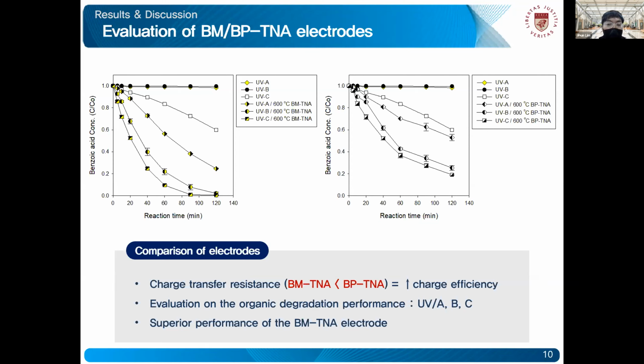Taking a look at the figure on the left, we can see that using the BMTNA electrode, benzoic acid was nearly completely decomposed, with even the minimum decomposition rate being 80%. But on the right side, using the BPTNA electrode, the degradation performance was quite low, and even the highest was only up to 80%, with the lowest being around 40%. So we confirmed that the BMTNA electrode showed a much higher photoelectrode degradation performance compared to the BPTNA electrode.